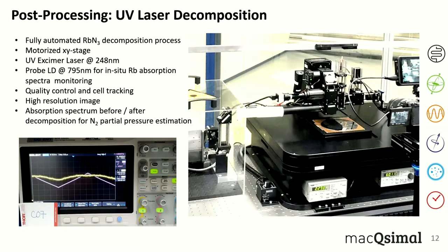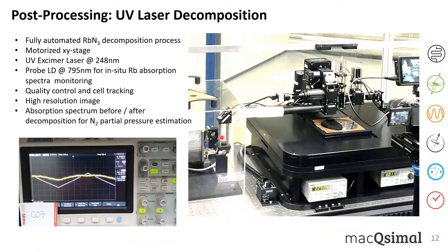Within the project we also developed a fully automated equipment to decompose the rubidium azide into metallic rubidium and nitrogen. You see here a motorized XY stage with a wafer on it. Then in this box, we have a UV excimer laser which emits light at 248 nanometer, which is directed with these mirrors onto the wafer.